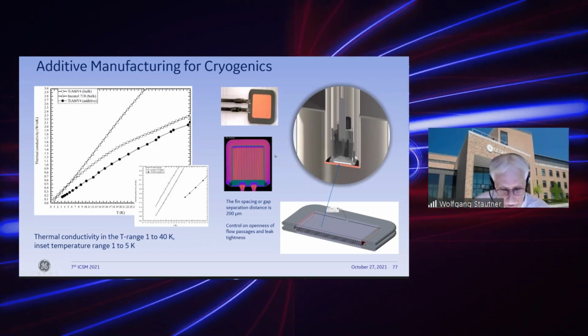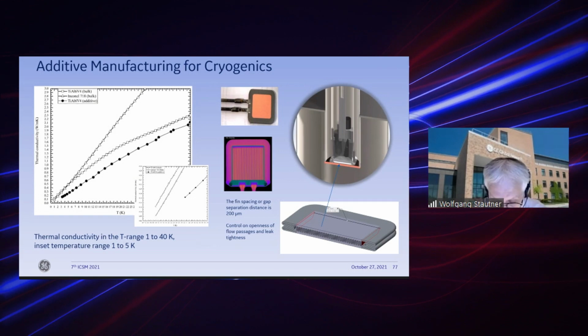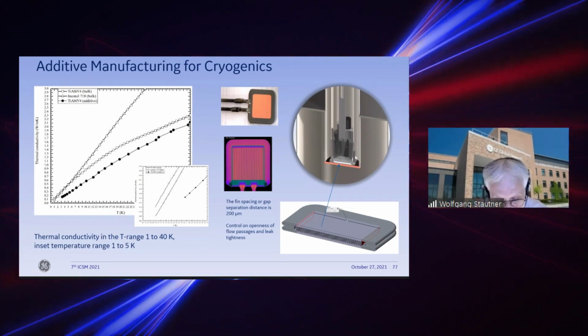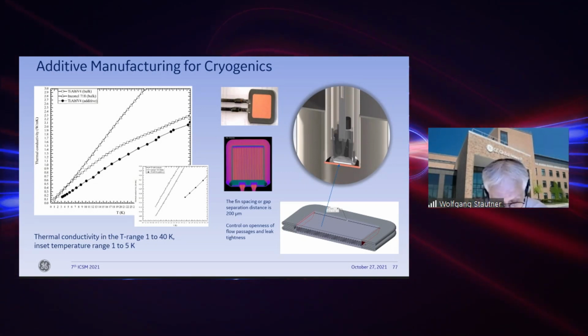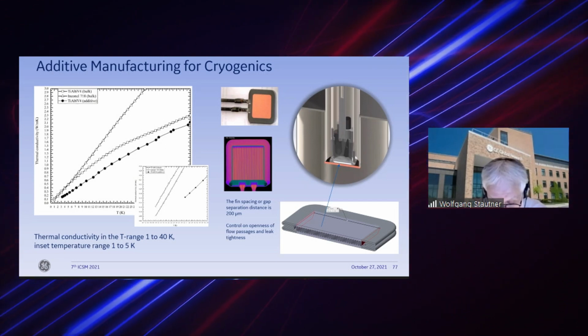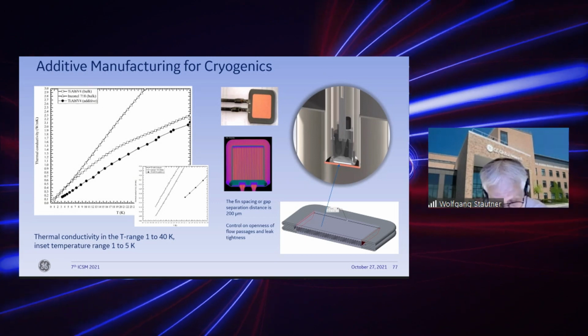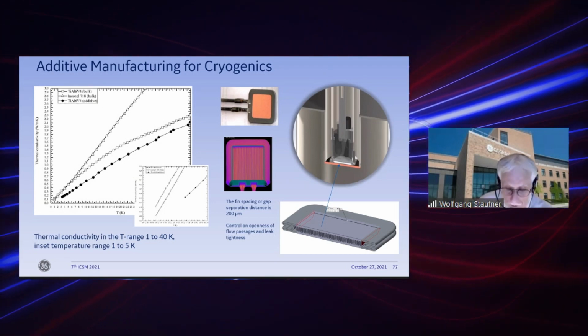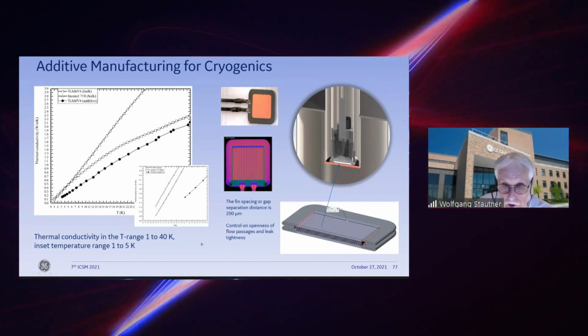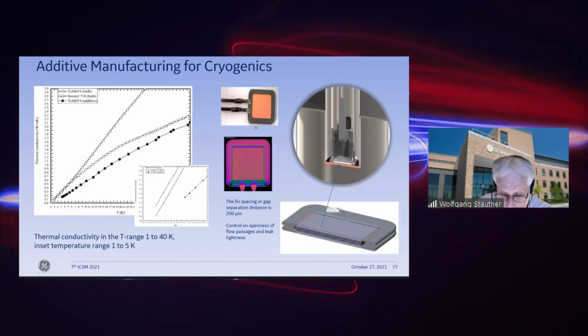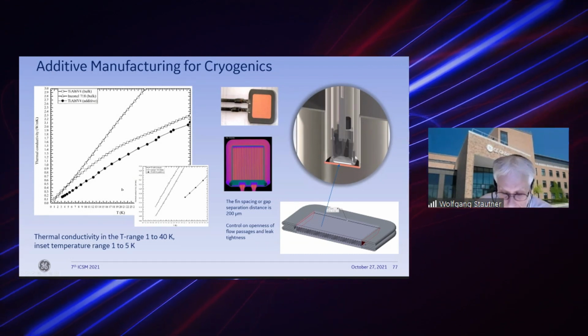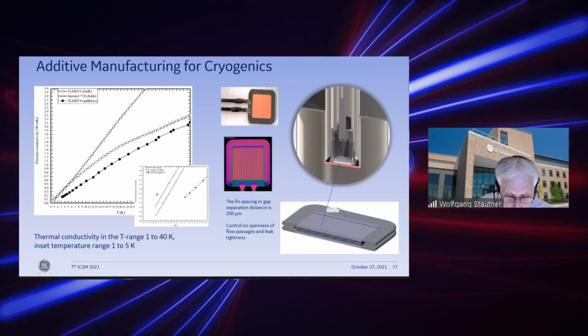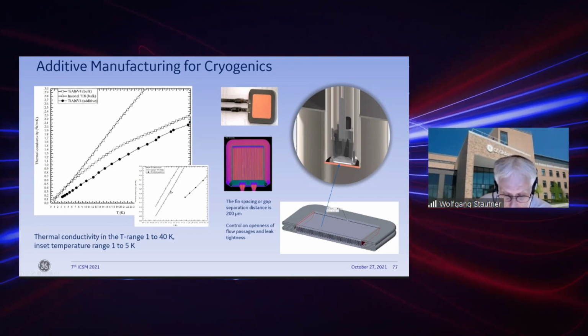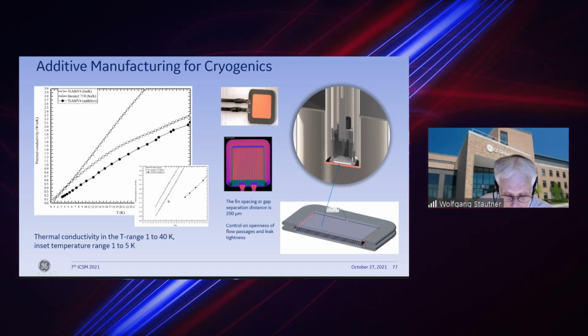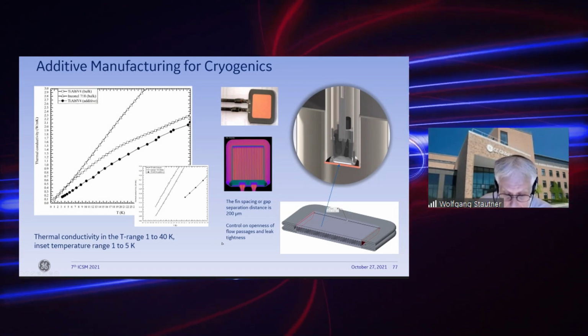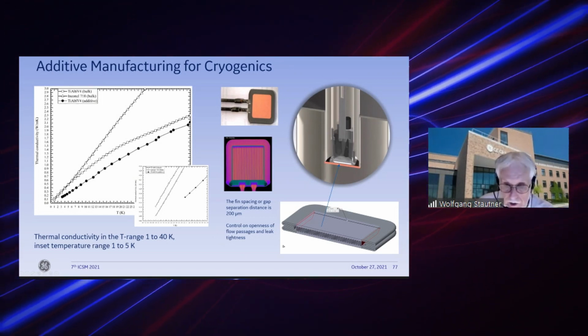However, the biggest impact and advance the cryogenics world is currently seeing is related to the latest progress in additive manufacturing. And to give you just one of many examples, here's an Inconel or titanium alloy-based gas gap switch for use at 1 Kelvin. And what you need to do here, apart from understanding the whole manufacturing technique, is you need to learn more about the actual material properties you are using in additive manufacturing. And this new technology enables that, finally gives us low cost access to materials we never had a chance to use in cryogenics commercially. And this is especially true also for delicate heat exchangers of pure copper.